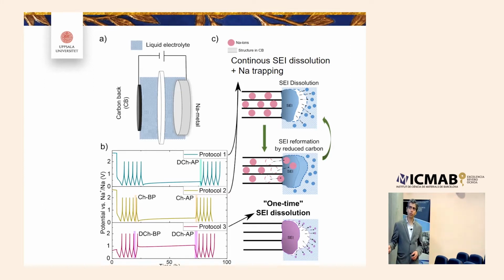We have been using three different protocols: if we cycle the battery for a few times and keep it at low potential, at such a low potential you're going to have continuous SEI formation. There's also a possibility of sodium ion trapping, because if you keep the battery at that potential and give it time, sodium ions will diffuse from the top surface of carbon particles to the core of the particles, and there's no guarantee you manage to extract all that sodium when you charge the battery.